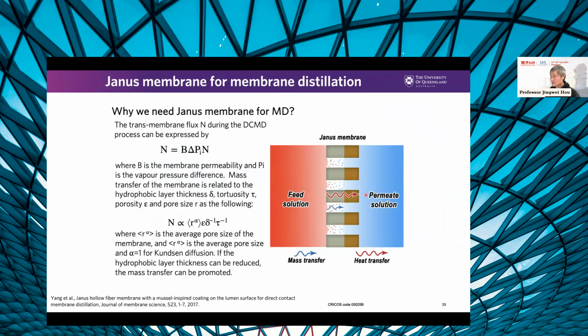In this case, you are the expert in the membrane. So we have the membrane. We are making one side treatment, but this is not increasing the thickness of the membrane. We're actually coating into the pores. Because polydopamine is pretty easy to control and quite stable, that's not really having too many incompatibility issues.